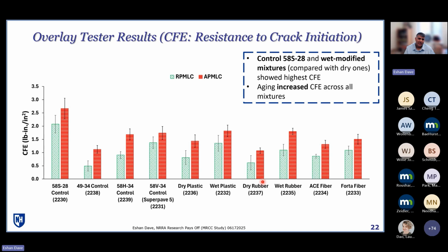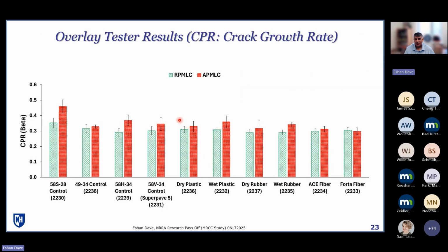To me, more interesting is really the second parameter that we get from the overlay tester, which is your growth rate. And there you want a lower value because you want a slower crack growth. You don't want a fast crack growth. And there you can once again see that after aging, all of these mixtures have a faster crack growth, which makes sense. Except some of the mixtures are more resilient. And keep in mind that these last two with the fibers show quite a bit of resiliency to this. Not surprising in this test setup at room temperature, because those fibers are really going to engage and provide the bridging action against your crack development. So they are carrying some of the load, preventing that crack from growing.